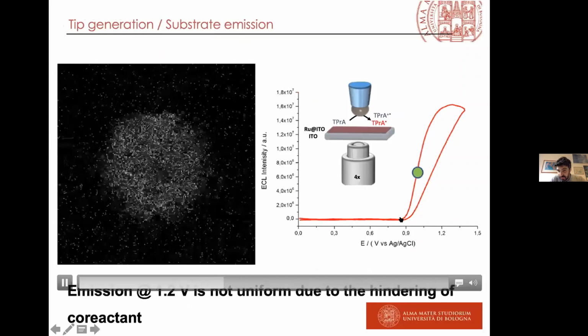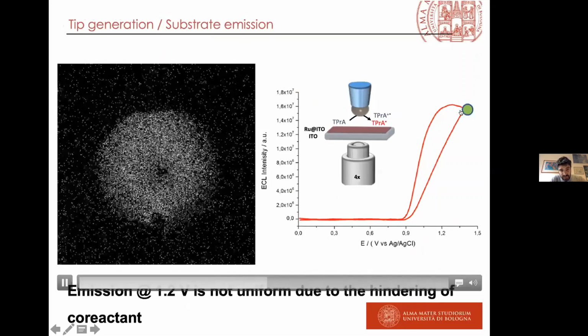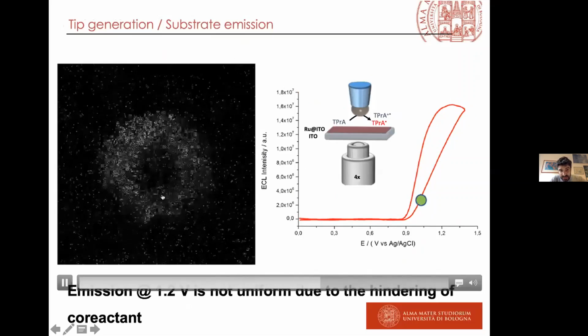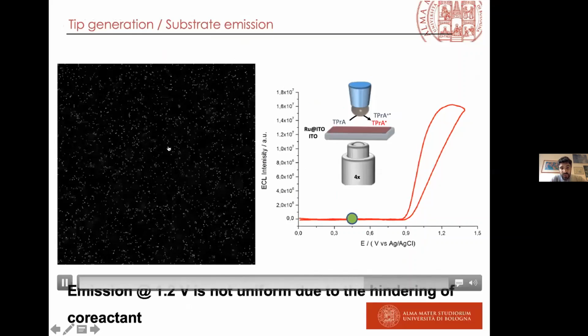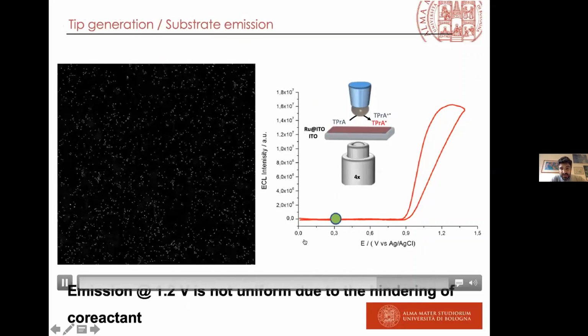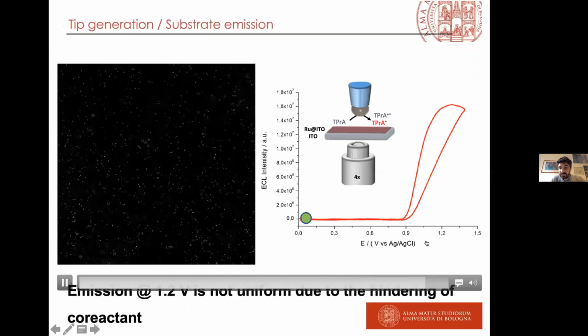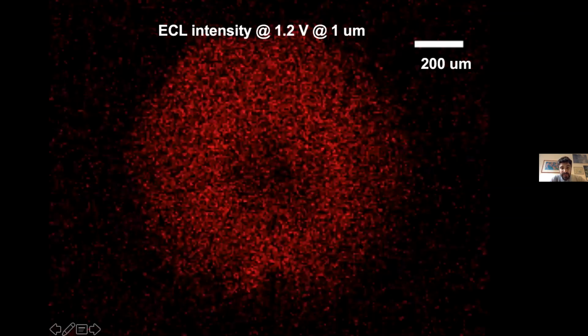We go towards the potential. TPA oxidation occurs at the tip, and we see the emission. But if you go more into the detail of this, if you zoom in on the emission, the map that we obtain thanks to the microscope, we see that the emission from the ITO layer is not homogeneous.